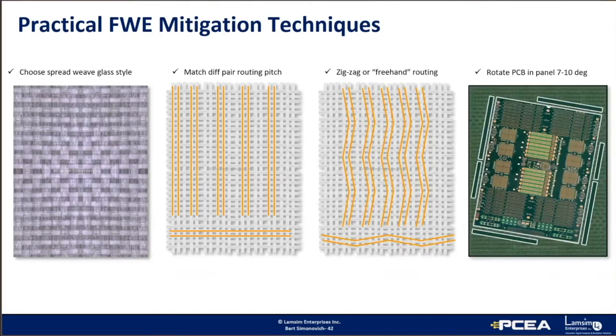And finally, rotating the artwork 7 to 10 degrees on the panel is often used, but it has cost implications because it often requires a larger panel size to fit everything. For many people, they complain about the additional cost. But my argument is, over the years, we have accepted cost increases for some of the following. There's high layer counts, low loss material, smoother copper, and especially back drilling of via stubs.